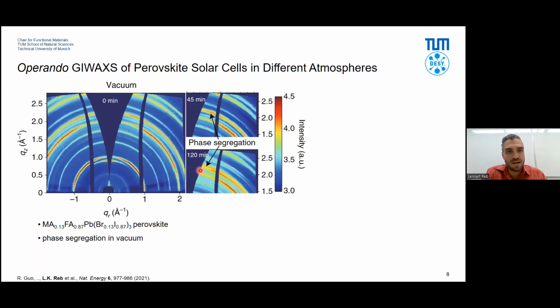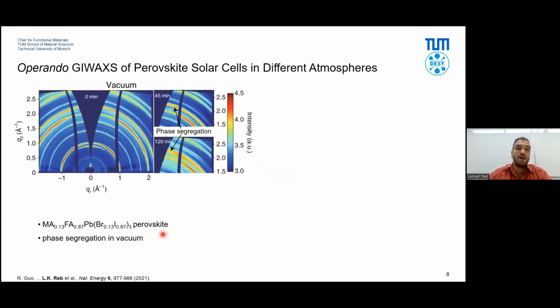What you can see is that there is a second ring occurring, and this is due to phase segregation. We're using this perovskite here, and then a pure FAPI phase is created. And this phase segregation actually just occurs in vacuum. How to analyze this further?